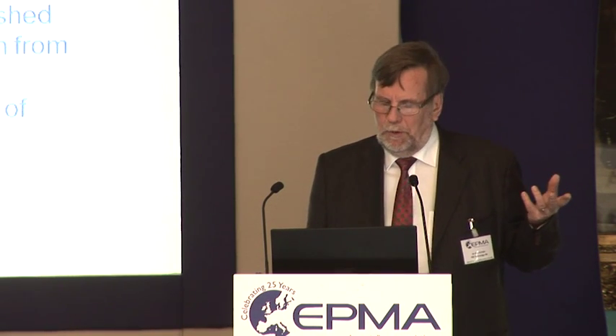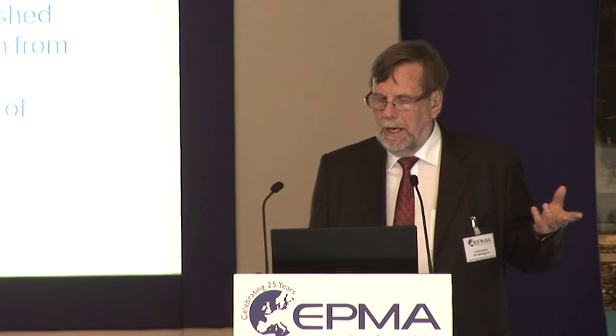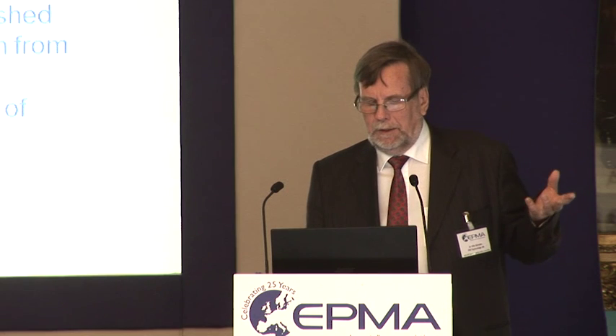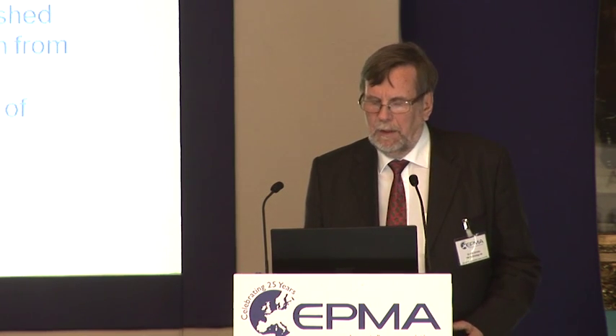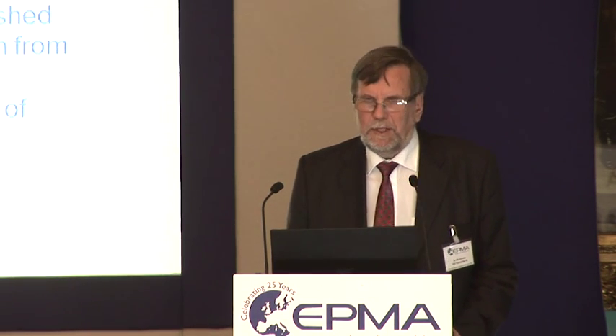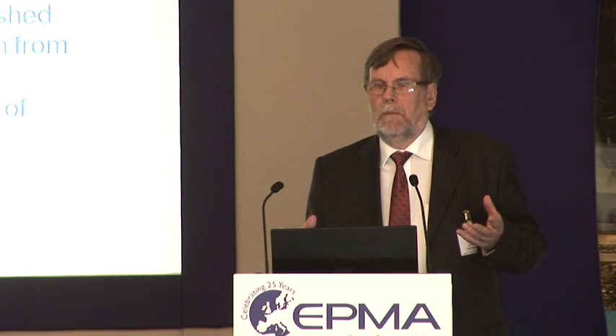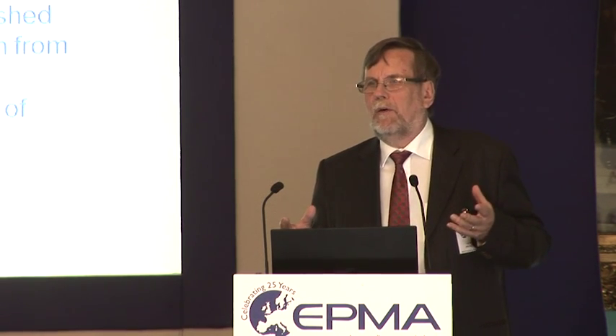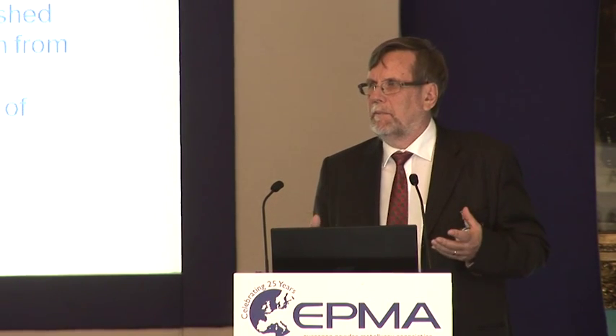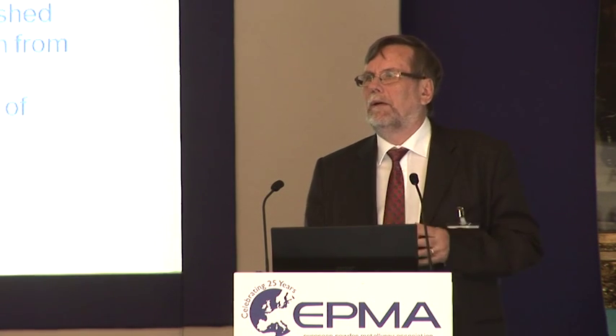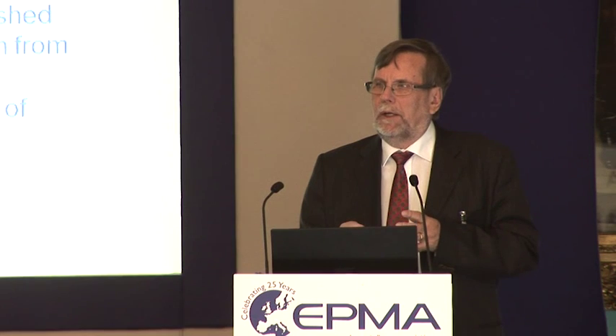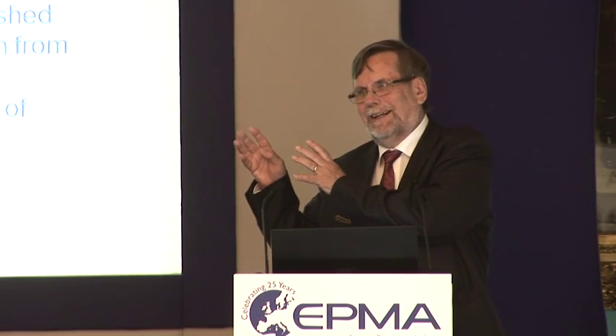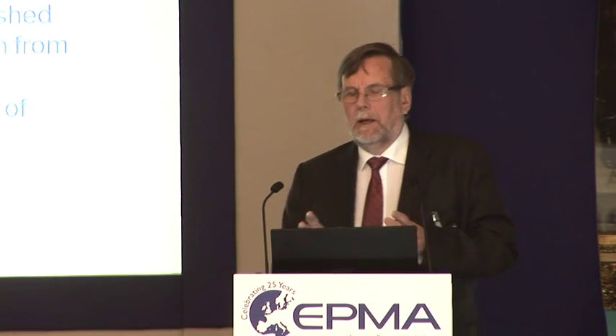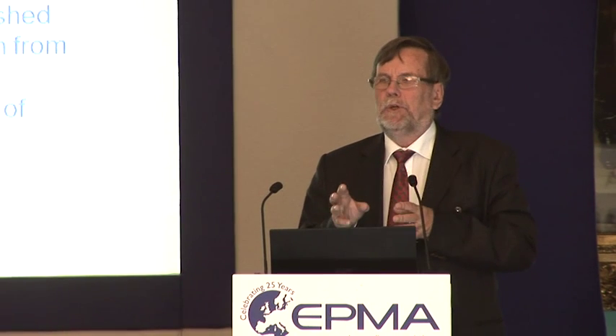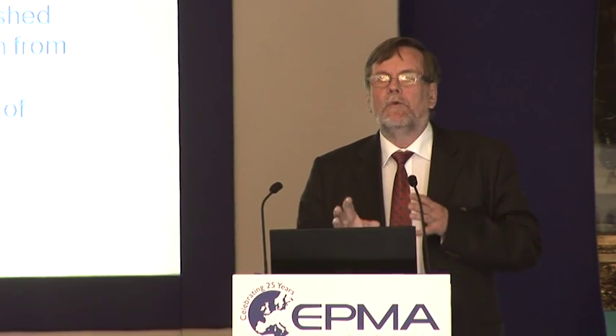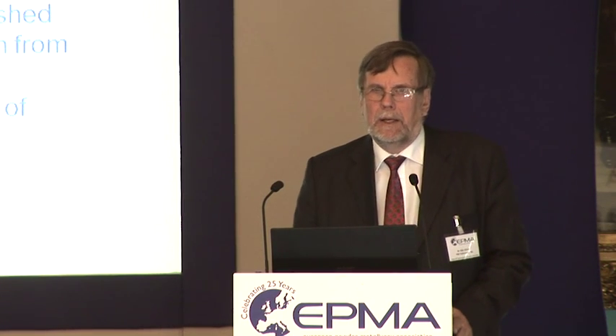The same will be for HIP units, conventional HIP units dedicated for pore closure of metal injection molded parts, already done, additive layer manufacturing, and conventional uniaxial pressing. The last is a little bit of speculation. If you look at a plant where you have production of high alloyed steels, which are difficult to cast, you can't use continuous casting. You have to do ingot casting. The yield of such a product by casting and forging to the semi-finished product is quite low. And with new modern HIP units and inert gas atomization, you will be able to do it competitively by the HIP process route.